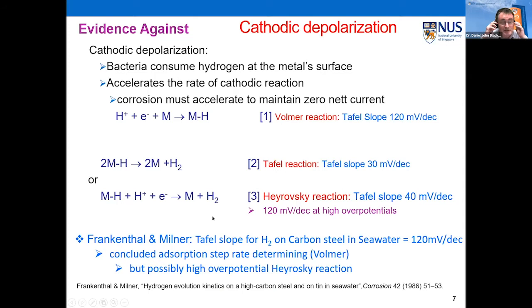If we go right back to our hydrogen evolution reaction, we have our Volmer reaction followed by the Tafel reaction or the Heyrovsky reaction. We can usually tell which one's dominating by measuring the Tafel slopes. About 30 years ago, Frankenthal and Milner measured Tafel slopes for carbon steel on tin in seawater, and they found Tafel slopes of 120 millivolts per decade.